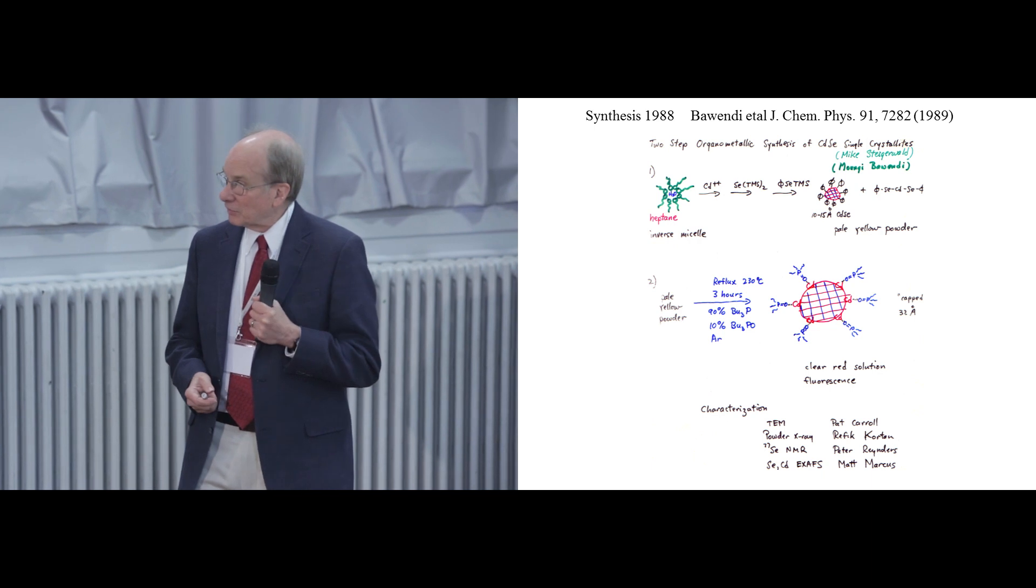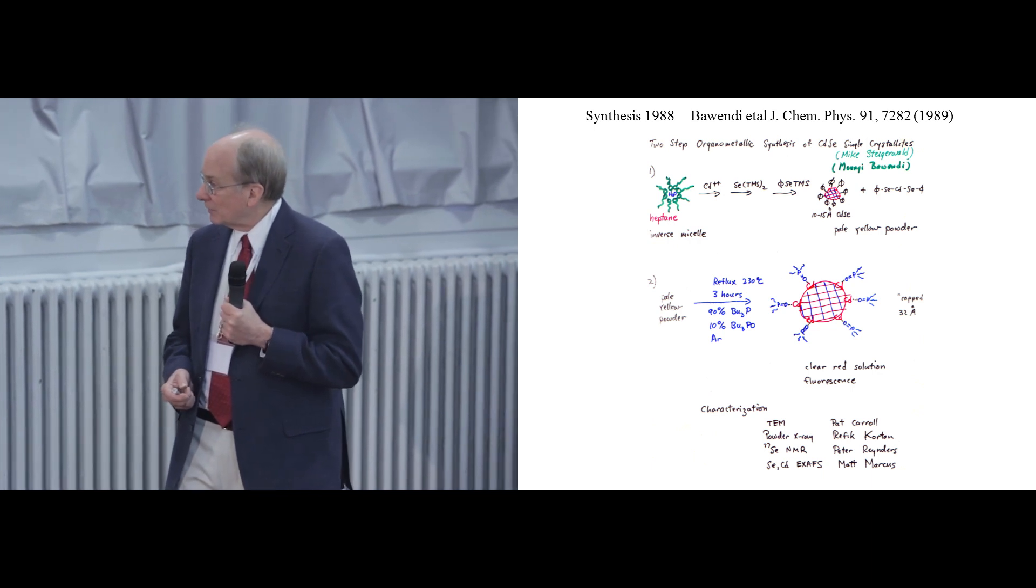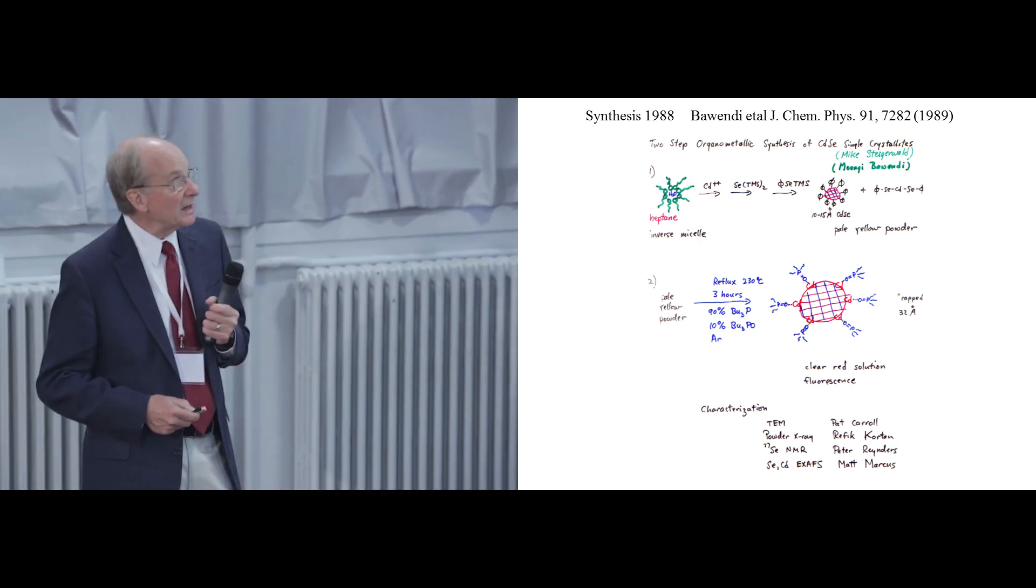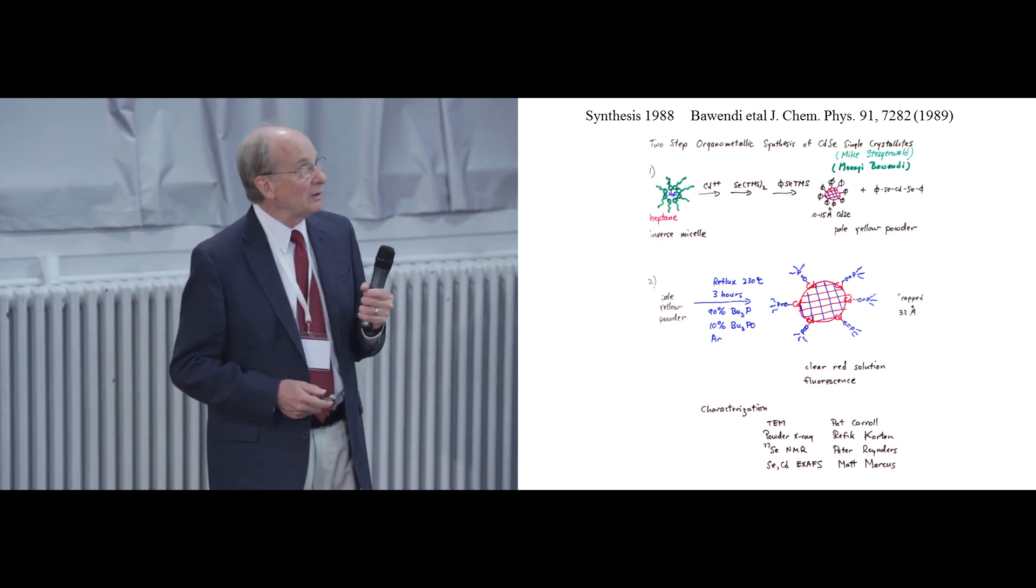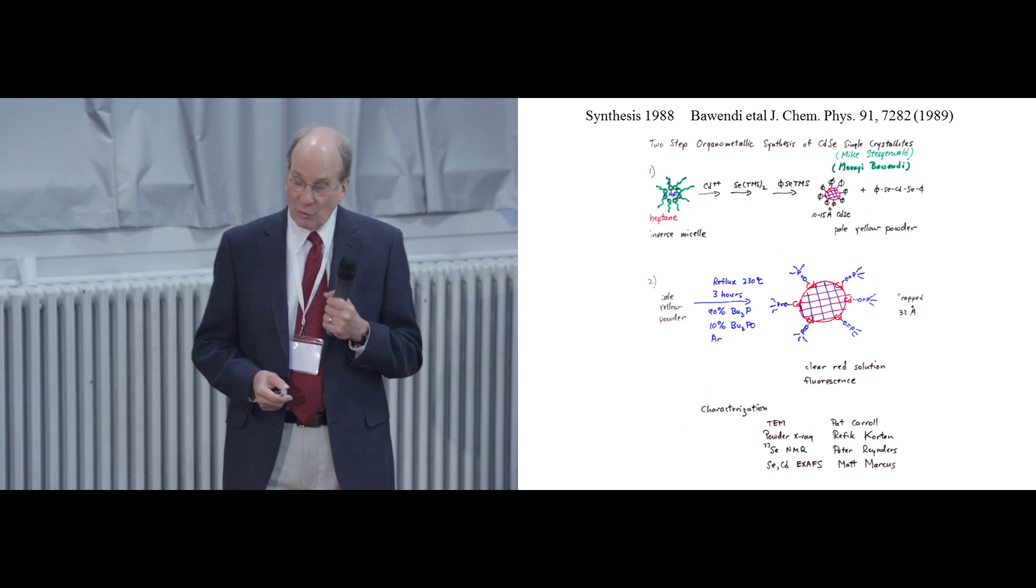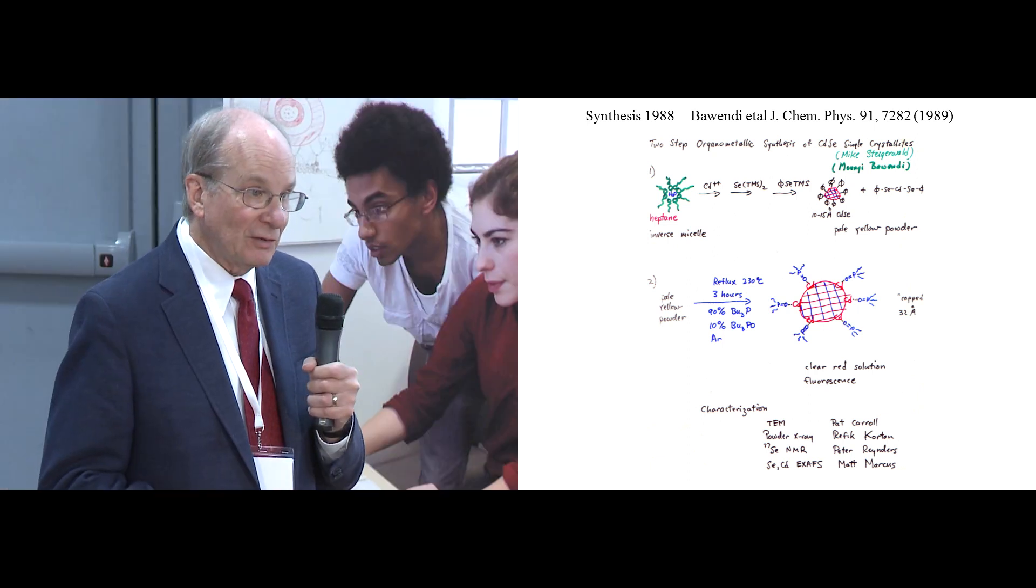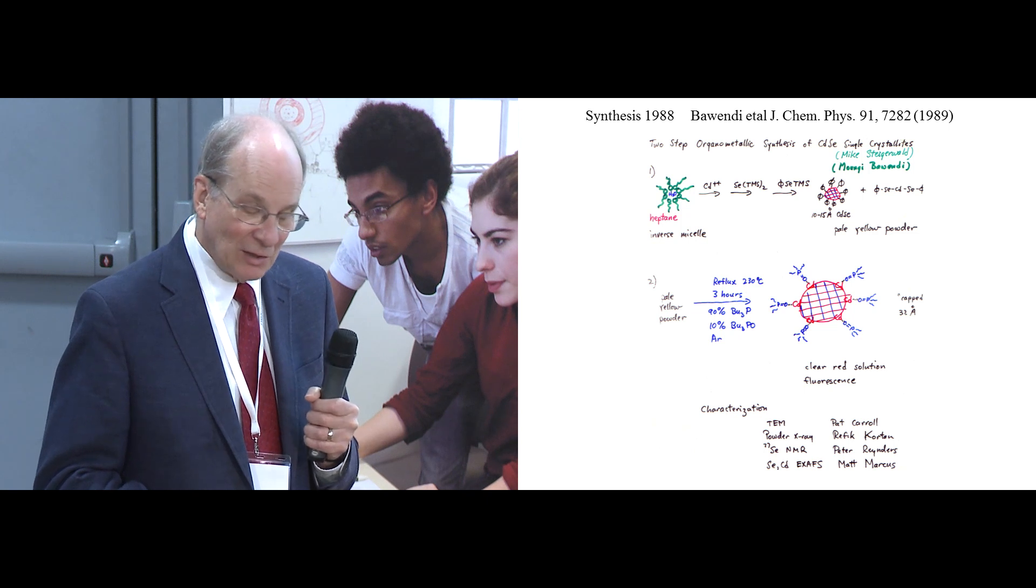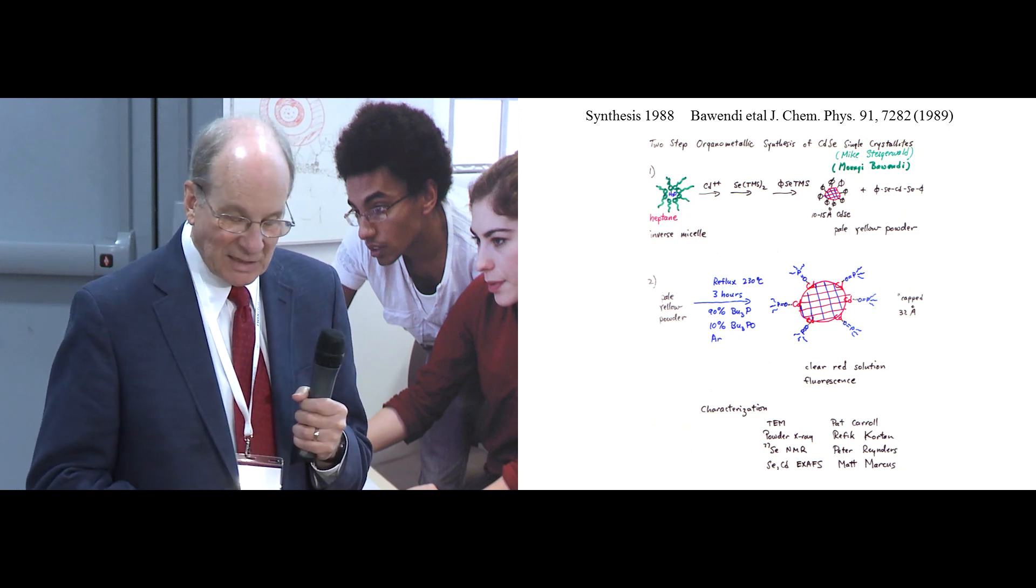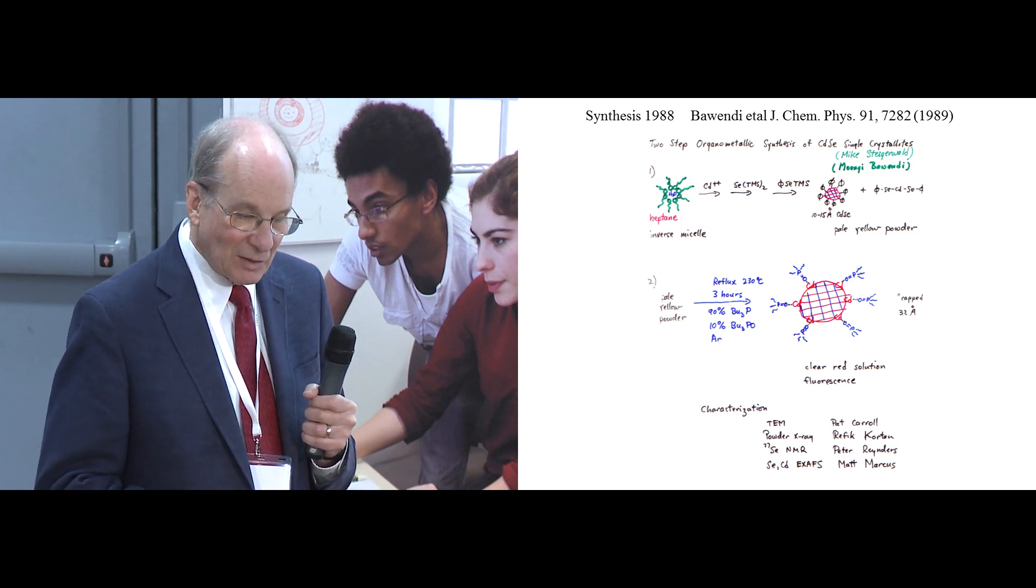I thought it was entirely Lewis base bonding, dative bonds from oxygen to the cadmium. We understand now that this is mostly wrong. Surface is not stoichiometric, and there's ionic bonding on the surface, as well as covalent bonding, dative bonding. And my young colleague, John Owen, will talk about this later in the meeting.